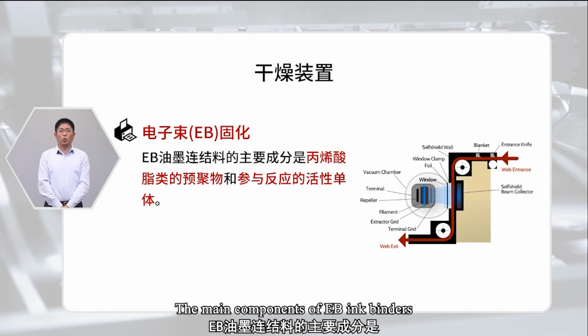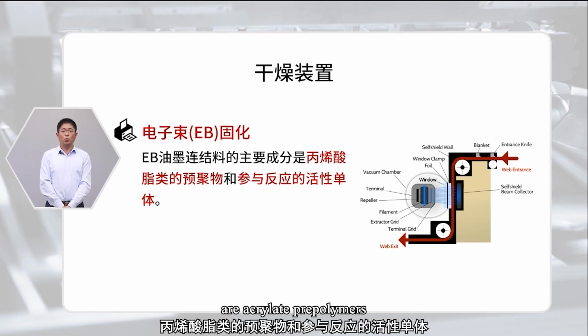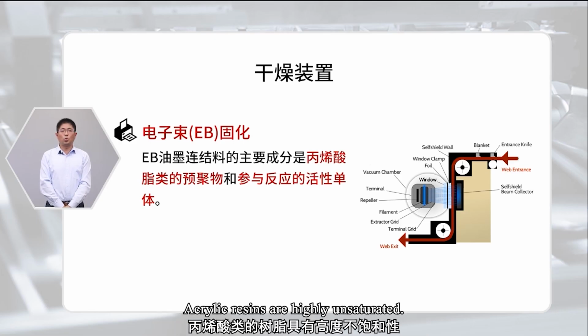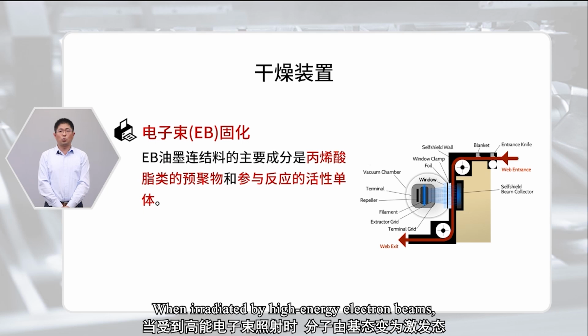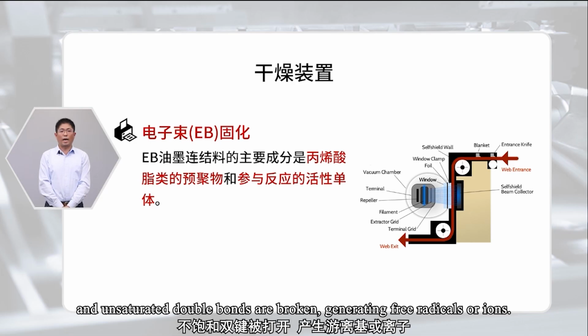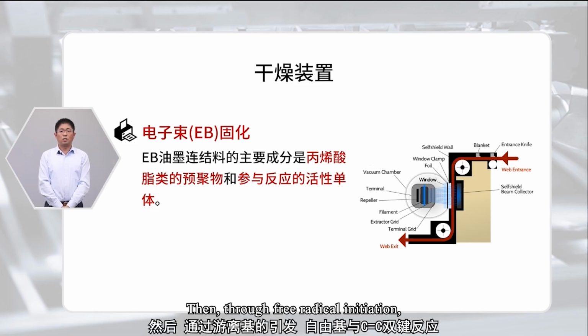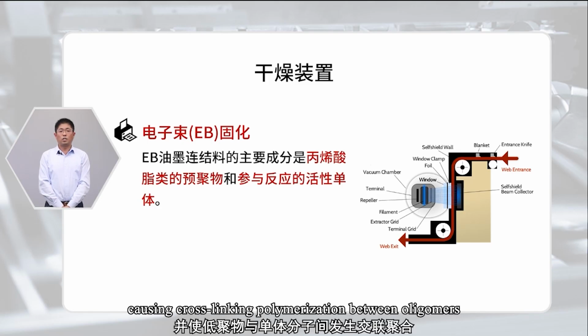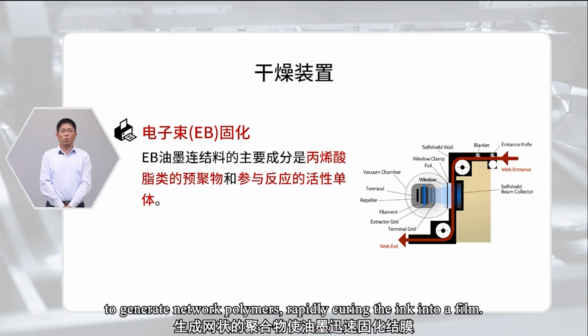The main components of EB ink binders are acrylate prepolymers and reactive monomers participating in the reaction. Acrylic resins are highly unsaturated. When irradiated by high-energy electron beams, molecules transition from the ground state to the excited state, and unsaturated double bonds are broken, generating free radicals or ions. Then, through free radical initiation, free radicals react with C=C double bonds to form growing chains, causing cross-linking polymerization between oligomers and monomer molecules to generate network polymers, rapidly curing the ink into a film.